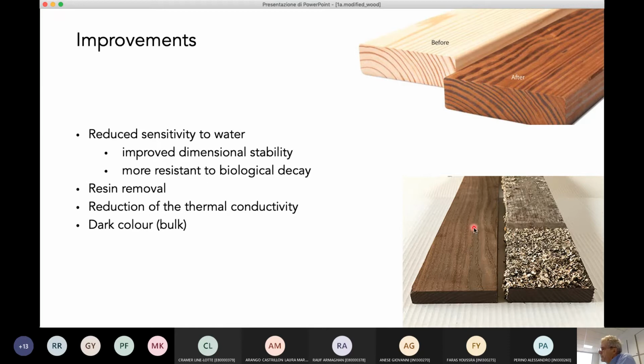You can see in this picture that the element on the right was not treated and the element on the left was thermal treated, and we see the aggression of fungi on the right and not on the left. Dark color for wood containing a lot of resin: the heating also promotes the removal of the resin. And because of the reduced amount of water inside the wood, the thermal conductivity is also reduced. The wood is more insulating.